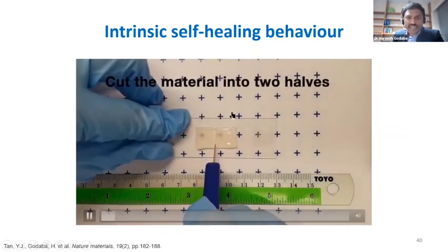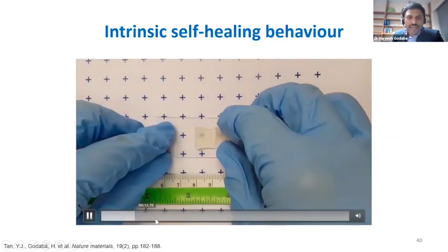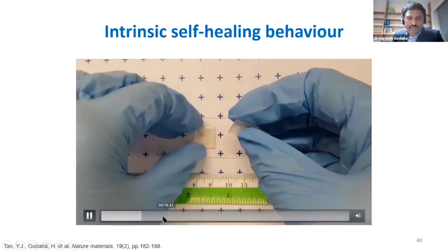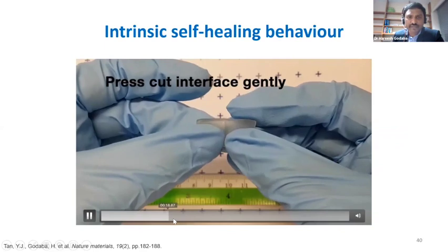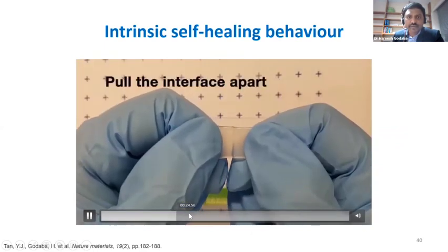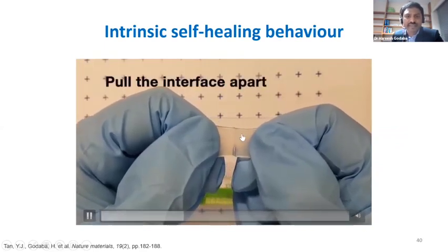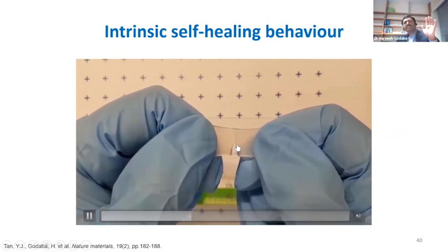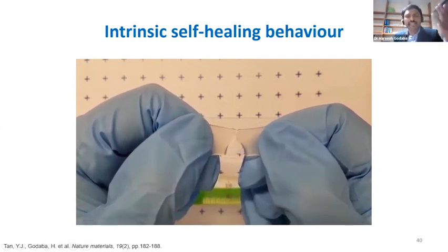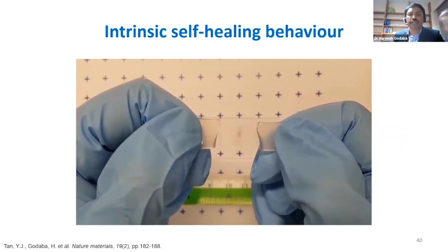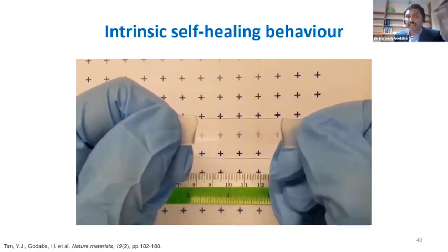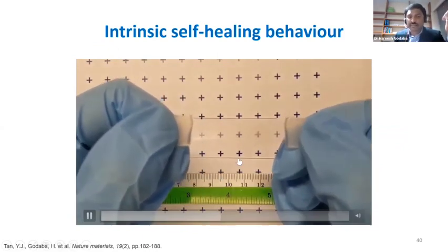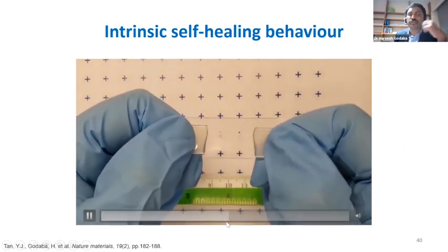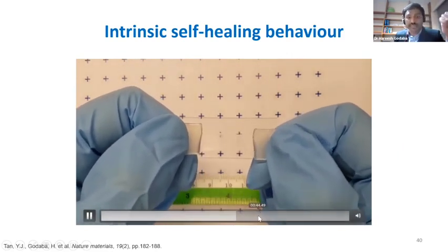So if you just cut the material into 2 halves, and then basically remove this, and then again put them together, and this is basically pulling this apart immediately. So what we can see is that it almost immediately begins to rebond in the cut regions. So that's the interesting part, that it starts to heal almost immediately.